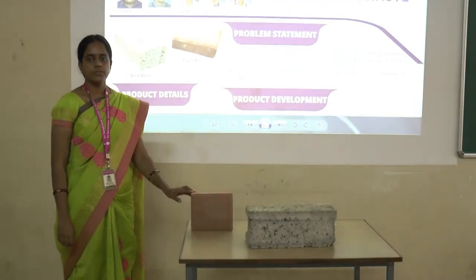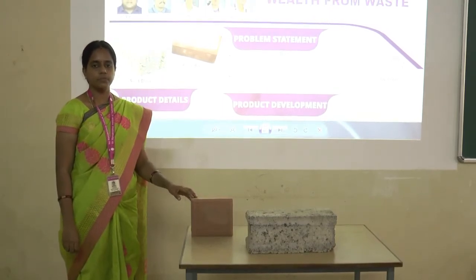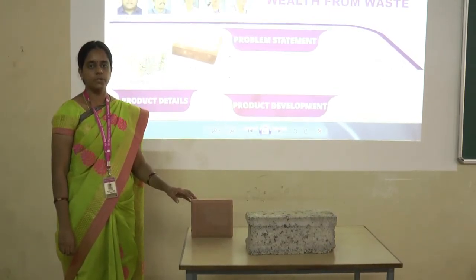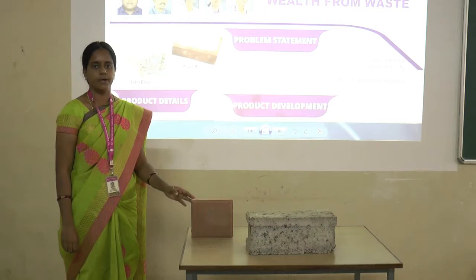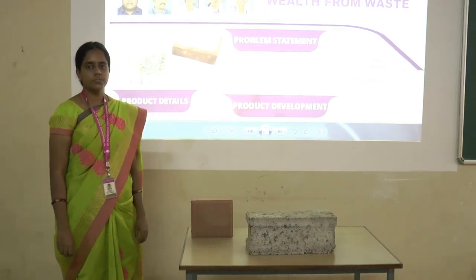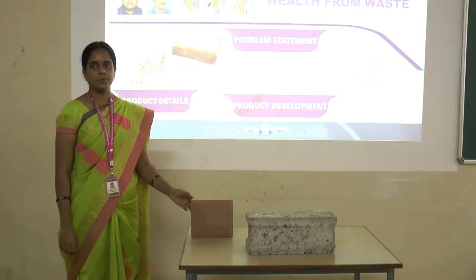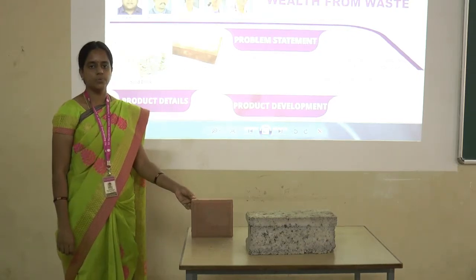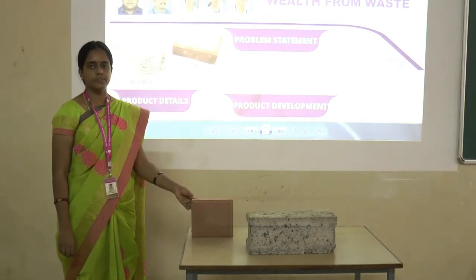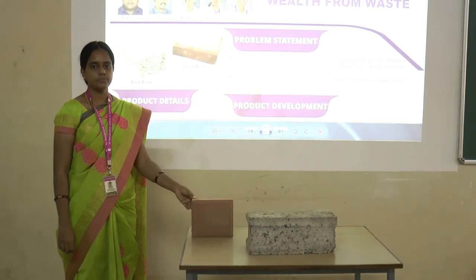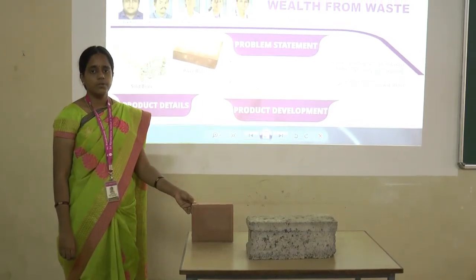paver block. The experimental work has been carried out for an M35 grade of concrete, in which the coarse aggregates were replaced with Bakelite. Natural coarse aggregates were replaced with 0, 2, 4, 6, 8 and 10% of Bakelite by weight. We have done